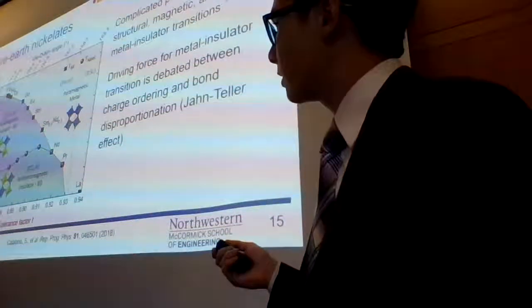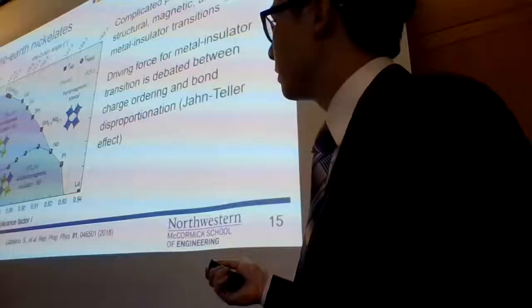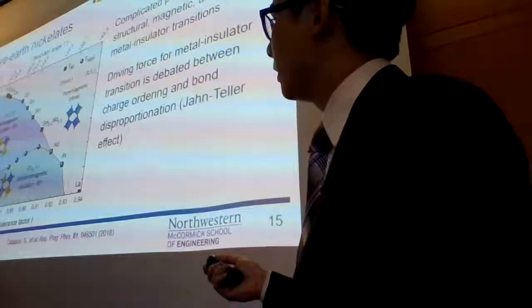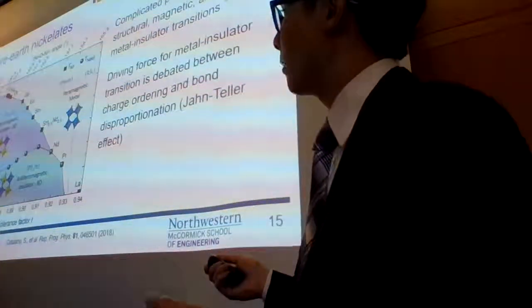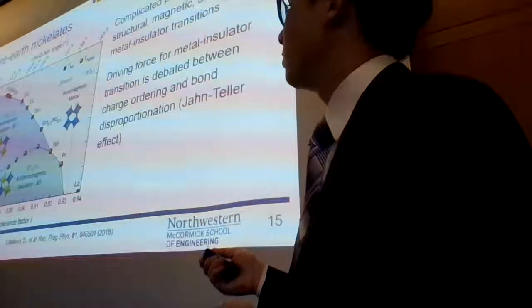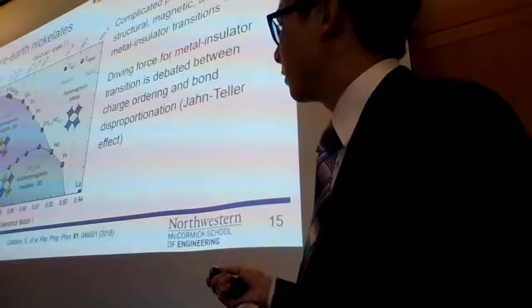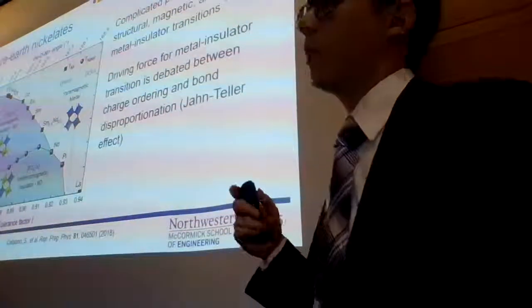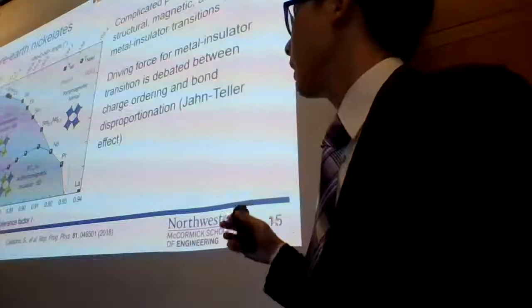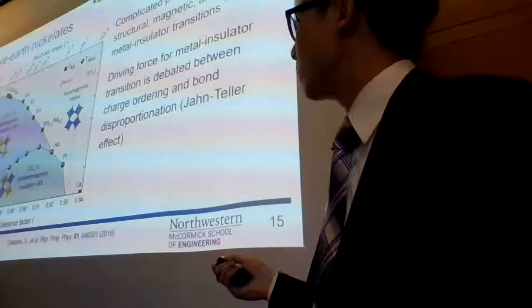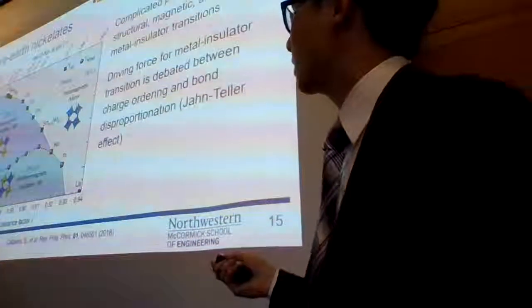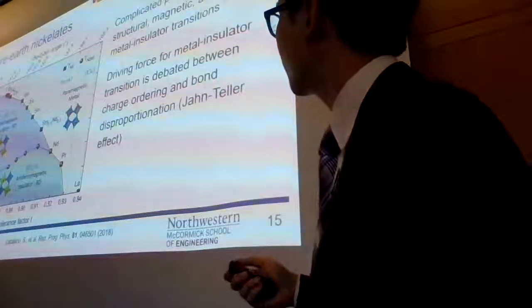paramagnetic metallic state through a metal insulator transition, into this purple region. At the same time they are going through a structural transition to a monoclinic phase, and at even lower temperature, they go to an antiferromagnetic ordering. Interestingly, for neodymium or praseodymium, the metal insulator transition and the magnetic ordering transition are at the same temperature.